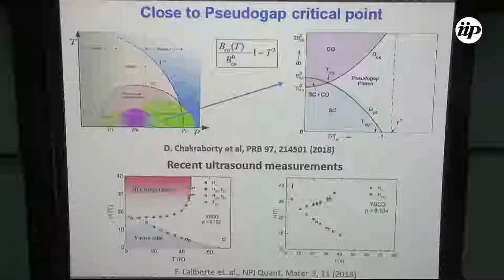There are some very recent experiments, ultrasound velocity measurements, where they measured the BT phase diagram in 12.2% doping, which is here. They saw that the flatness is there. But if you go from here to 13.4% doping, then you will see that the onset field now depends on temperature. We have not fitted it with this data, but you can clearly see that there is a very good temperature dependence on the onset field, and it's no longer flat.